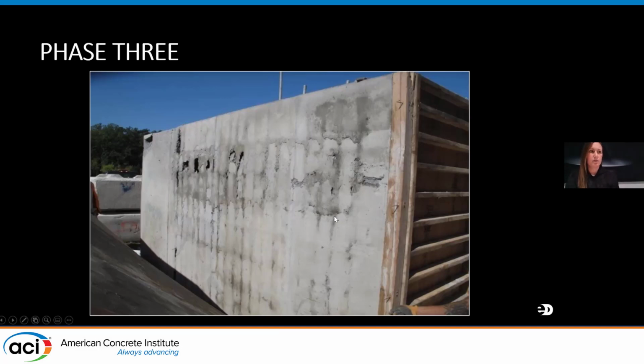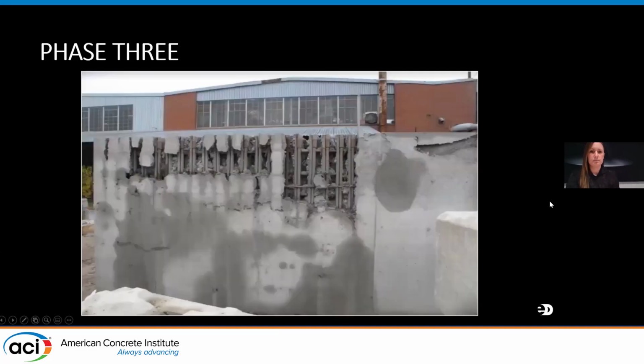You can see that there's reinforcement shadowing and large voids as soon as we stripped the wall, and then just taking a hammer to it. You could see that there was a thin, basically shell in many areas that were hollow once we hammered on it a few times. So the difference in the quality of the two mock-up walls opened our eyes to how contractor dependent the process is, and it can definitely be done right, but you need to have properly trained nozzlemen and inspectors for the application that they're going to be doing.